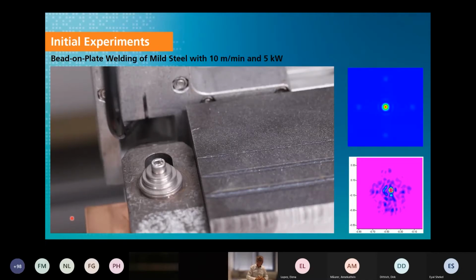We have also done the first trials with just a peak in the middle. This is seen here: this is programmed, and this is what we got. Just quite recently, we removed the microspot monitor from the XY table, put a piece of mild steel underneath the laser, and did a linear bead on plate welding of mild steel with several speeds. What you can see in this short video is done with a speed of 10 meters per minute and a power level of 5 kilowatt, as a very first usage of the laser in our lab for material processing. So I will run this video.